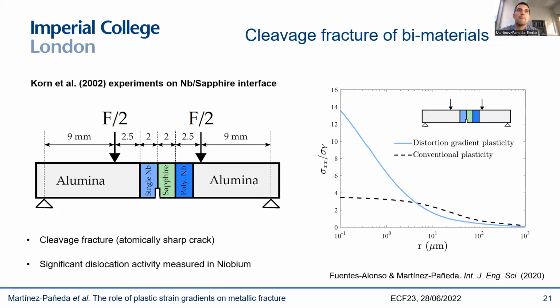within the bi-material. And what we see when we use one of these strain gradient plasticity models, in this case Gurtin's distortion gradient plasticity model, is that when you account for the role of GNDs and plastic strain gradients, your stresses are high enough that you can attain this cleavage fracture strength that we discussed before. So in this set of experiments, for the loading conditions that they consider, we're able to get critical stresses that are high enough over a sufficiently long distance such that a crack can grow.